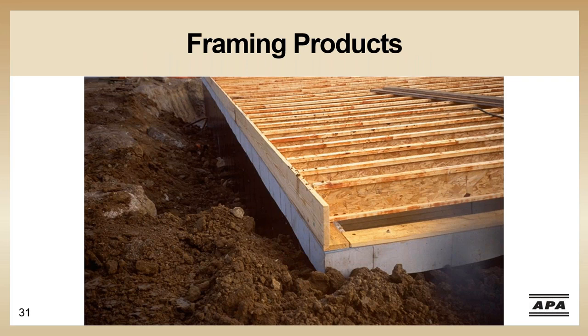Because engineered wood floor and roof systems use low moisture content I-joist, structural composite lumber, and rim board materials, it's recommended not to mix lumber into that system. This is for two reasons: the potential shrinkage of the lumber and the potential minor expansion of the I-joist. It should also be noted that I-joists and lumber have different depths, which can lead to continuity issues. In this picture, a framer used a solid lumber rim board with an I-joist floor system — the depths don't match, which is an issue.